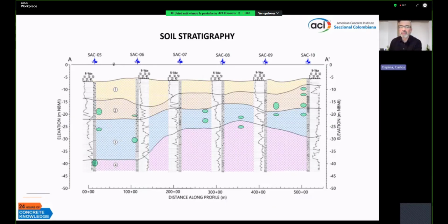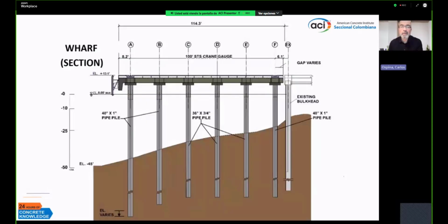The soil stratigraphy shows a combination of multiple strata of clay and sands, and the soils display setup. That means that the piles that get driven into it gain capacity with time. This is a cross-section of the wharf. It's not quite the typical marginal wharf where you have a very steep slope, but because there is a structure behind, there was a need to have a steep slope, but it is marginal because it's against the shoreline. So every bent has 6 piles, and the ones on grids A and F support heavy cranes.